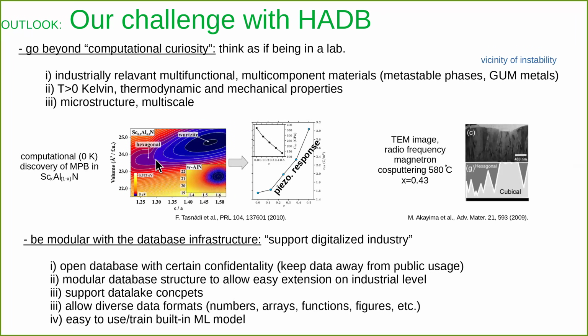actually competing energetically with each other. So again, I refer to the vicinity, and that will result in something extraordinary. In this case, it is a giant piezoelectric response. But then you go into the lab, and you deposit it with some magnetron sputtering. So you ask your colleagues, come on, do this deposition. And then you characterize it with TEM, let's say, and then you will see such a situation. So, relatively high temperature deposition at this concentration, very close to what was investigated here.